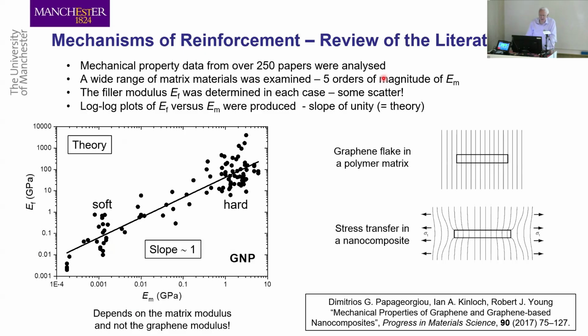In fact, we analyzed data that people have got in the literature, where we looked at the effective modulus of the graphene on this axis on a log-log plot against the modulus of the matrix. Because we found that with the soft matrix materials, the graphene tended to have a low modulus. With the harder materials, graphene tended to have a higher modulus. And we put our own data on this, our natural rubber, there's our polypropylene, fitted in the literature data. And this had a slope of 1.